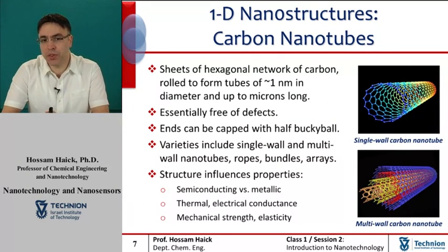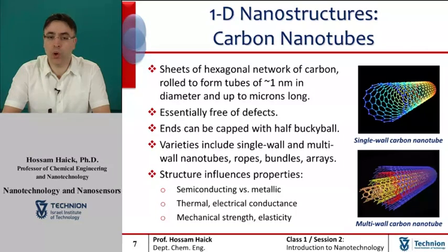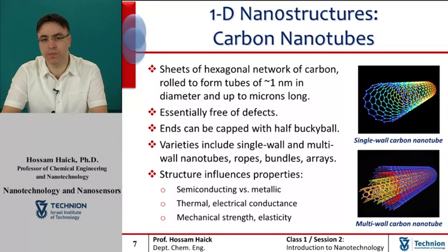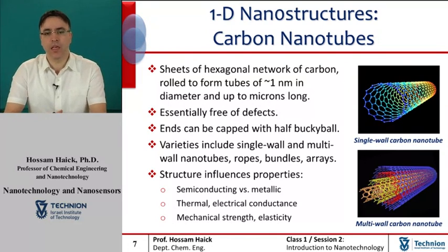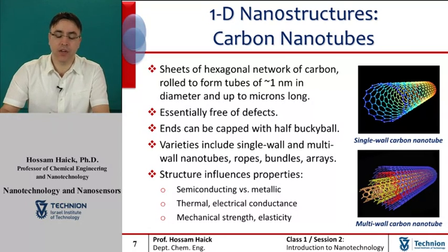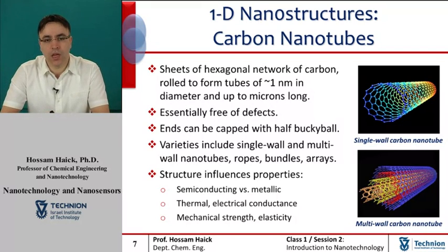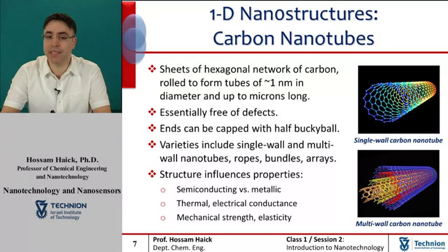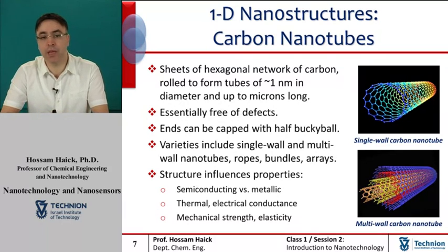We will move now to carbon nanotubes. Carbon nanotubes are long, hollow structures with walls formed by a one-atom-thick sheet of carbon, commonly called graphene in the scientific literature. These sheets are rolled at specific and discrete chiral angles, and the combination of the rolling angle and the radius determines the nanotube properties. Individual nanotubes naturally align themselves into ropes, held together by van der Waals forces — or, more specifically, pi stacking. Usually, the ends of carbon nanotubes terminate with a half-buckyball-like carbon structure.